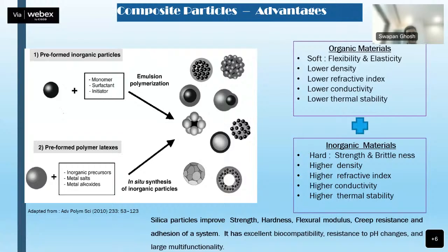Option B is that we can do the opposite. We can take a polymer particle, and then in the presence of the polymer particle or polymer latex, we can add an inorganic precursor, metal alkoxide, or metal salts, the way we like to build the inorganic matrix. For example, in the case of silicon oxide, we can use different types of silicon precursors and build those silica particles on top of the latex. But usually, in most cases, it is observed that silica particles actually go inside the polymer materials.